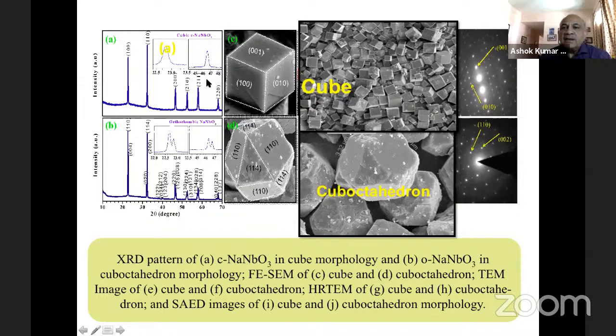So here we are concentrating on two shapes, where in one you are making cubes and in the other you are getting octahedrons. Now, if you have this cube, as you know, in the cubic structure, all the faces will have the same energy, whether you are looking at the 001 or 100, etc. These are crystallographic planes. Whereas in the octahedral kind of geometry, your planes will have slightly different surface energy. So this is indexed as the 114 phase, and this is the 110 phase.